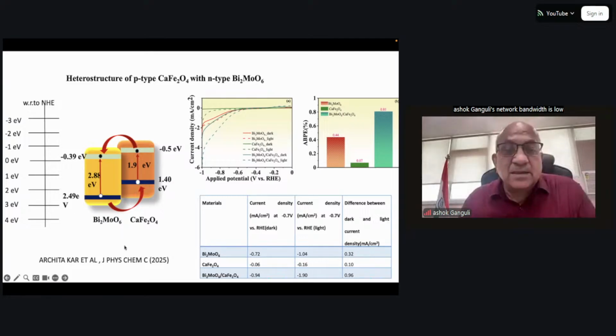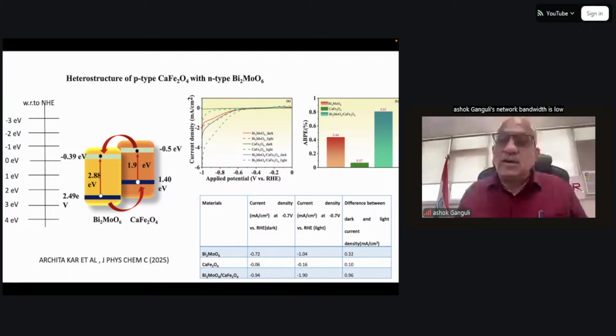And this is a recent paper where again the same energy level diagram of the two semiconductors has been chosen. So you choose the semiconductors knowing where their conduction band edge and valence band edge are, and you can create this heterostructure which will facilitate the transfer of electrons to one of the semiconductors and transfer of holes to the other semiconductor. And when you have this transfer of electron to one semiconductor and hole to another one, you are increasing the lifetime of these charge carriers, and you are reducing the chance of recombination of it.